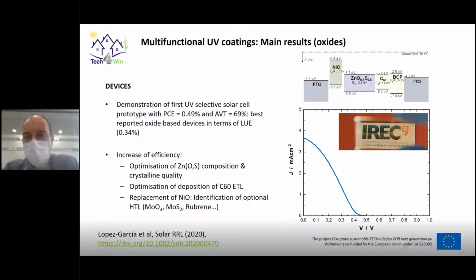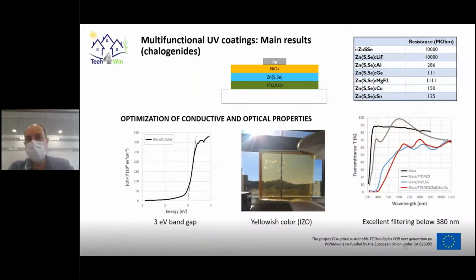So we are working on the identification of alternative optimal hole transport layers. Essentially, we are working with three candidates: molybdenum oxide, molybdenum sulfide, or rubrene. In terms of multifunctional UV coatings, we are also working on the chalcogenides approach. In this case, essentially, these are zinc sulfoselenide layers that are deposited on FTO substrate.